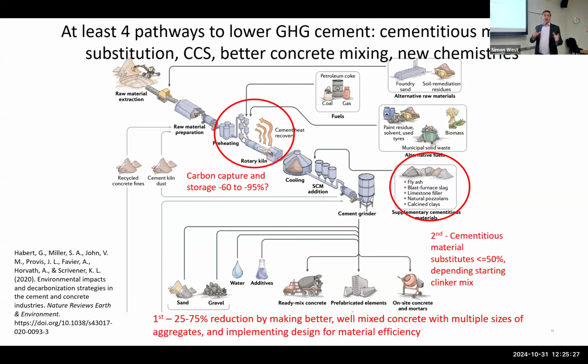I helped with a French study where they have 25 cement plants in France that they expect to need. Only 5 of them are anywhere near CCS geology. And their idea was on those 5 plants, they'd put CCS and they'd make all the clinker, but then they'd ship that clinker by rail to the rest of the country where it would get ground up and mixed into various types of cement and made into concrete where it's needed. So ideally, if you do as much of this as possible, then as much of that as possible, you only need CCS on about 20 to 30% of the actual cement production.